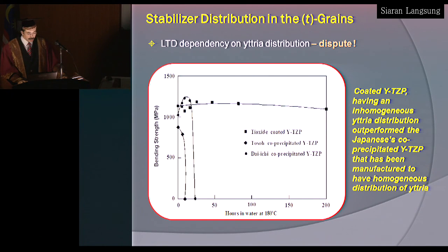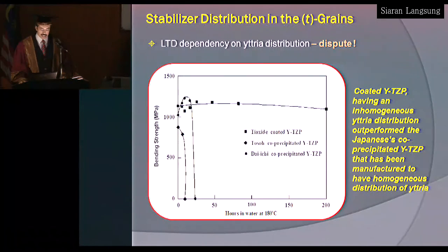Now again, experimentally it has been shown that this is not the case. What the graph shows is the effect of aging, or LTD, on the bending strength of this material. As you can see, the two Japanese powders, Tosoh and Daiichi, are co-precipitated zirconia powders. They degrade or break up within less than 25 hours of exposure in a steam environment. In the case of coated powder, where the starting material, the yttria, has been coated onto the material, it survived for more than 200 hours.